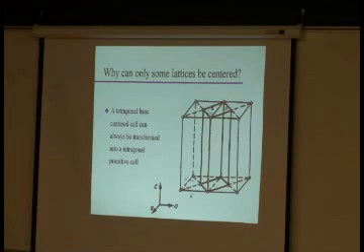In that case, which cell is preferred? And I think that is what you were referring to, Indira. The smaller cell is preferred, right? So that one is the preferred cell. Not because it has higher symmetry, but because it has the same symmetry and it is smaller. You can do that with any base-centered tetragonal cell. I made no assumptions about that cell, except that it is tetragonal. Okay? So that is why there is no base-centered tetragonal lattice. It cannot exist.